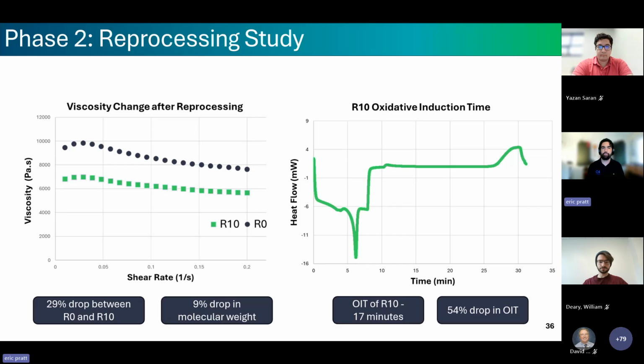So after 10 full reprocessing cycles, the material is still mechanically sound and still oxidatively stable. And that's really the whole point of this project. We're not just trying to divert XLPE waste once, but providing a blend that can be circular and exist in the recycling stream for some time without losing properties that make it usable in the first place.